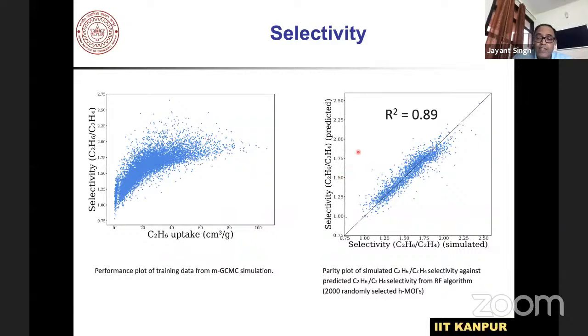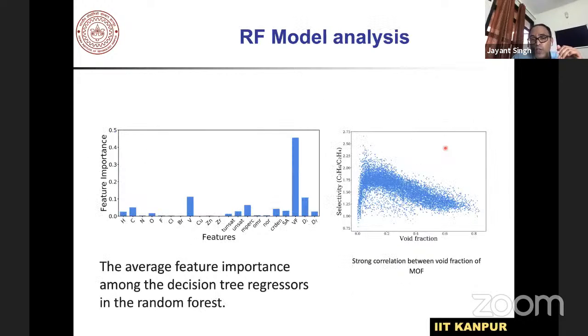and this became our database to train the model. Subsequently, we have taken another 2000 randomly selected MOFs and obtained the selectivity from the predicted model. Then we also simulated them, and we found that the prediction and simulation are in pretty good agreement. So that gives a strong confidence in the model we have developed. The other thing which we have done is identify the features which are important in our random forest model, which in this case we have considered. Here we found that the void fraction in the MOF plays an extremely big role. When you look at the selectivity of ethane as a function of void fraction, you can see that selectivity is highest at a certain void fraction.